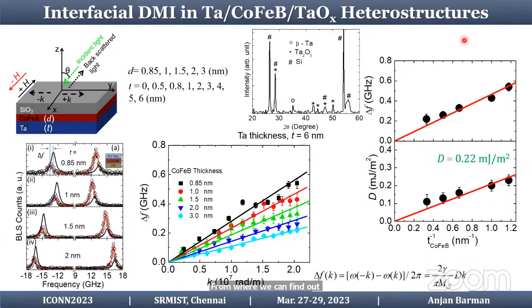So here we actually show the Dzyaloshinskii-Moriya interaction in the cobalt iron boron and tantalum system. Tantalum is a heavy metal, as we have already shown, and we varied both the tantalum layer thickness and the cobalt iron boron layer thickness. We find from the Brillouin light scattering experiment that there is a clear asymmetry in the spin wave, and we actually modeled the delta F, that is the variation in frequency for K plus and K minus, that is, spin waves propagating in two counter-propagating directions.